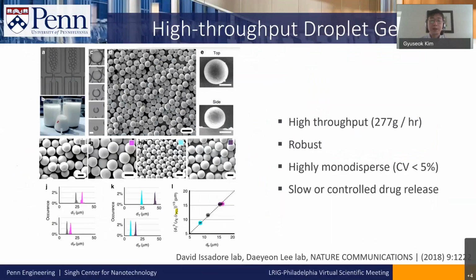So this is a very good research result in terms of high throughput. They were able to make 277 grams per hour through this method. This research was published in 2018, and they made an even higher throughput device and published another paper in 2019. This device is very robust because it is silicon-based. They use silicon and glass, not PDMS. And this is highly monodispersed. The coefficient of variation is less than 5%. And we can use this for slow or well-controlled drug release.